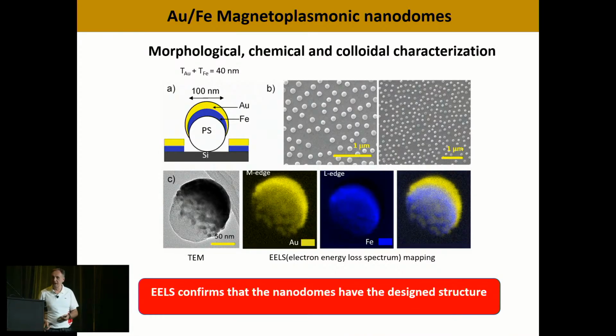To make sure that we really have the structure we designed, we did some electron energy loss spectroscopy mapping in the TEM, and you see here the TEM picture I showed you before. When we measure at the gold edge, we see a big shell here. When we measure at the iron edge, we see that the shell is smaller. So when we overlay the two images, you see that we have an iron shell, and on top of that iron shell, we have a gold shell. So we indeed have the structure we designed.